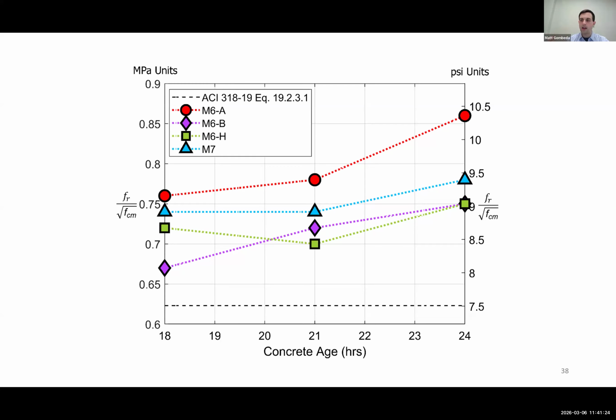higher than 7.5. And you might look at it and say, well, 7.5 versus 9 isn't that much. But when you actually do the numbers and look at the stresses, it does have a pretty substantial benefit for the precast industry. So it does make a difference. Even if it's a little bit conservative, there's still some room to dial it in a little closer.